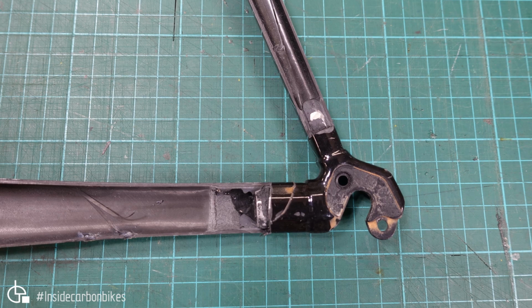The dropout design is an aluminium piece which is bonded in, and you don't see many issues with that at all. The older ones, we used to see the bond break down over time. I've replaced or rebonded a few of them over the years, but the newer ones seem to be a bit better. They've got a barrier ply of glass in that interface area. So yeah, that's all pretty good.